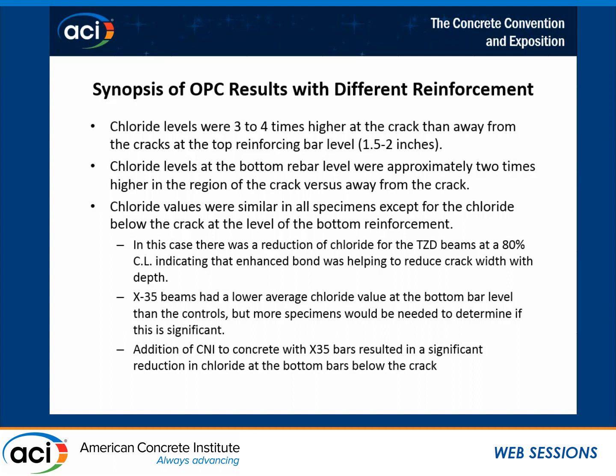The chloride values were similar in most specimens except for the chloride below the crack at the level of the bottom reinforcement. In this case, we saw a reduction for the TZD bars, which had a high surface area, and we also saw a reduction for the X-35 bars, especially when you had calcium nitrite present. And I think this is important: where the rows of cracks might play, what your rebar is, is something that needs to be considered.